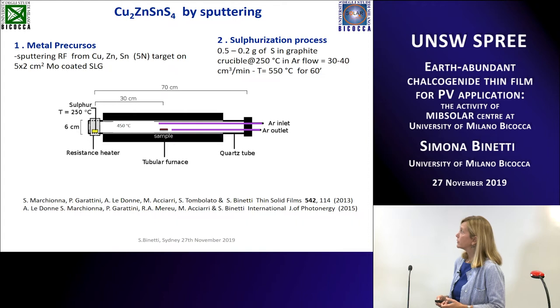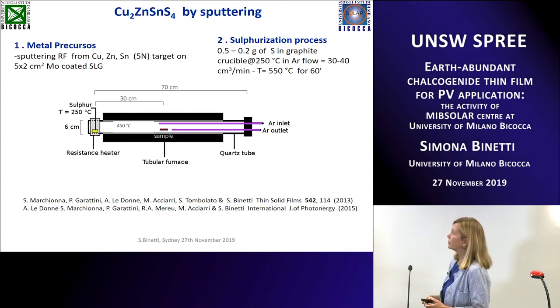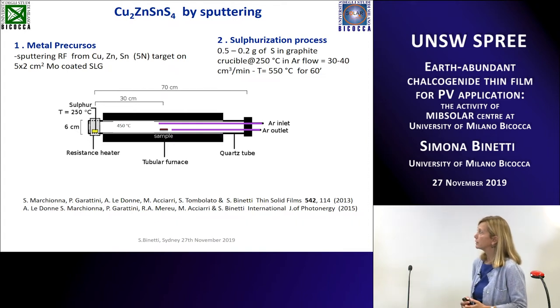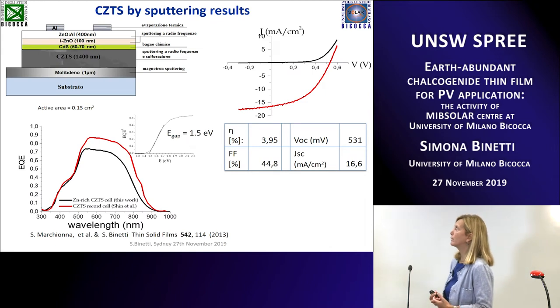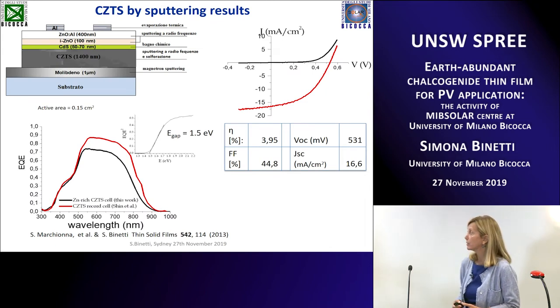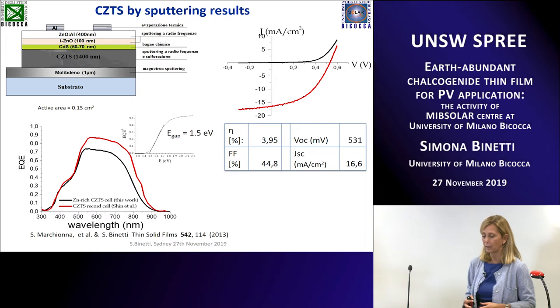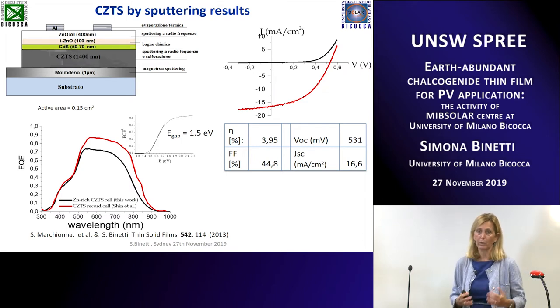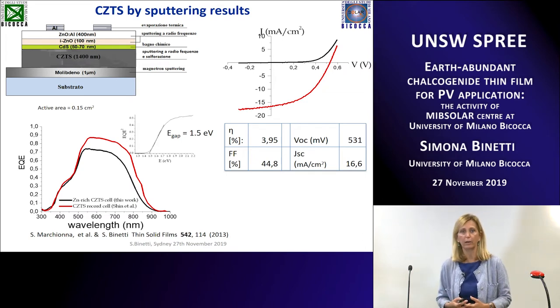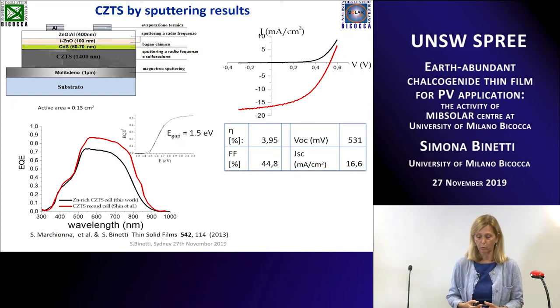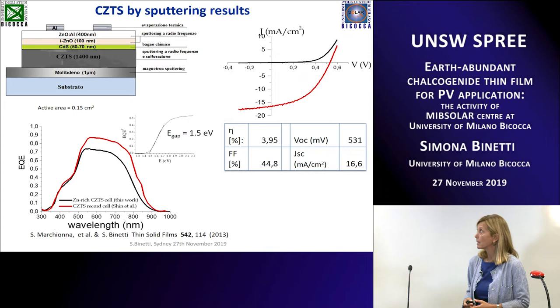We developed the system, and we're starting with efficiencies around 4%. That was not so bad, but it's quite far from the record efficiencies at that time and also now. So we decided that the gap between our efficiencies and the record efficiencies obtained in other labs was too big to continue with these techniques. And so we decided to develop a new type of process